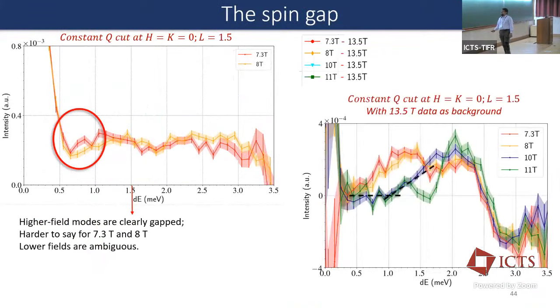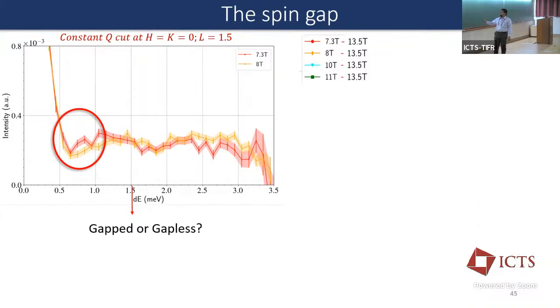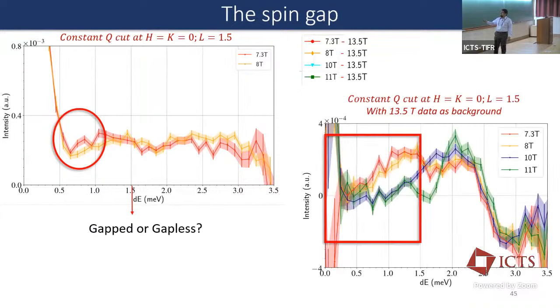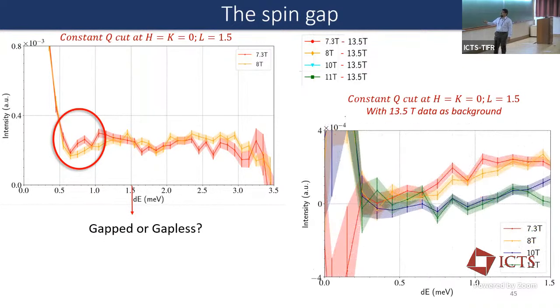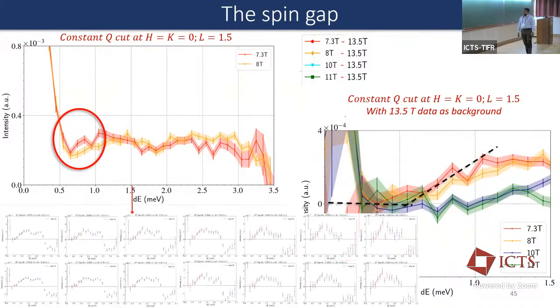And what we find, at high fields, of course, we can fit it to a gap where you basically subtract the 13.5 Tesla data. So it looks like you have no scattering right here, and then you have this rise of a mode. So this inflection point is what you call the gap. But can we do the same thing for the 7.3 and 8 Tesla data, which I have zoomed in here? Can we say for certain that it is gapped? That's basically what we are going through right now. And can we fit it to something like that?